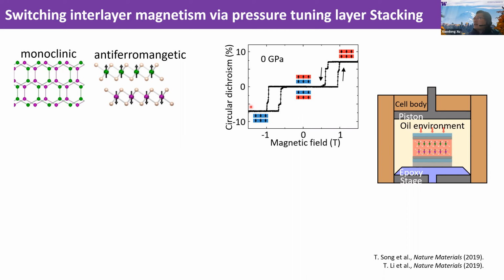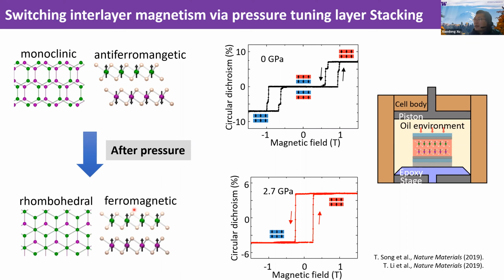If I perform these circular dichroism measurements, you'll see typical behavior for a bilayer: vanishing circular dichroism near zero field, then after the spin flip transition, the signal comes back. Now we apply pressure and change the layer stacking. Then the crystal becomes rhombohedral. Then we measure this circular dichroism again.